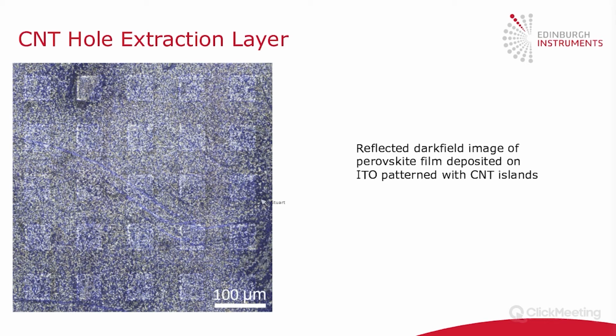Shown on the left here is a real picture now of this patterned carbon nanotube substrate. This is taken with a reflected dark field image, so white light illumination and looking at the reflection of that white light back to the camera. And you can see the pattern, so that each of these little squares corresponds to an island of vertically aligned carbon nanotubes. And then this dotted structure on top of it is the perovskite. It looks grainy because perovskite typically deposits in different grain sizes, which is responsible for these black dots.